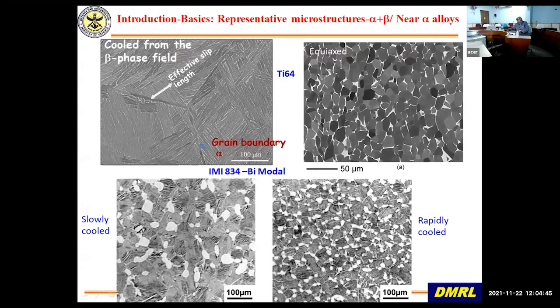Now here again, Ti6Al4V, when you beta heat treat, cool from the beta region, you get this kind of colony structure. You can see different colonies of alpha, and you can see the geometric pattern. This bright thin layer is beta, and in between, darker regions are alpha. You also can see grain boundary alpha formation, because grain boundaries are a high energy region, and alpha first precipitates on these grain boundaries, and that deteriorates the mechanical properties. So you have to take care of it.